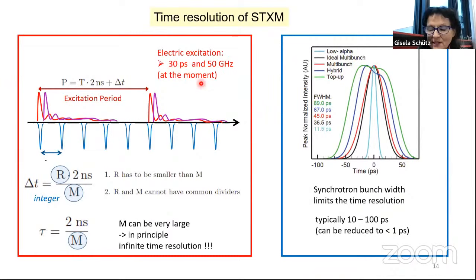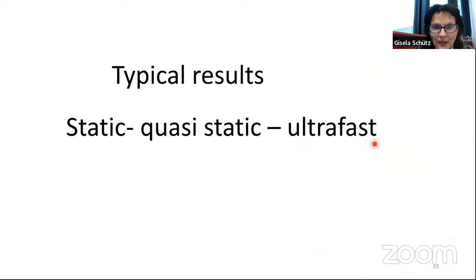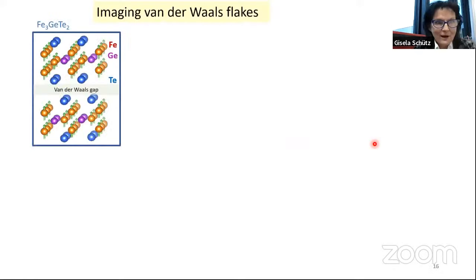And the time resolution, we do in the following. You can shift the excitation period with respect to the period of the synchrotron. And if you use, for these delta T, you can use the following expression. You have here two integers, where r has to be smaller than m. And they have what is important, that they have not common dividers. And this m is given by the channels you have to sort. In principle, it can be extremely large. And so this is the time resolution, can be very well, from this technique, very well below nanoseconds. So at the moment, we have an excitation possibility up to 50 gigahertz of pulses of 30 picoseconds excitation. So this fits all together. And now the limit, what limits us to higher frequencies is the width of the synchrotron bunch.